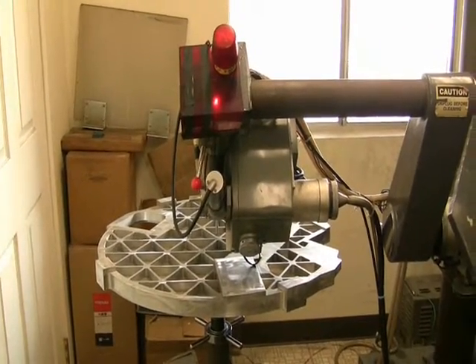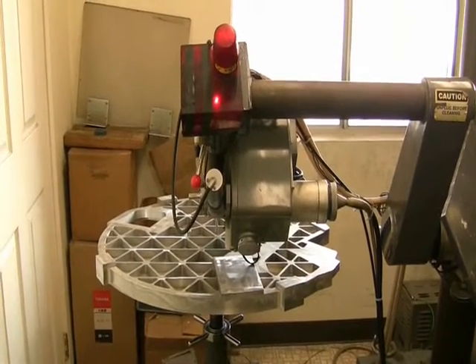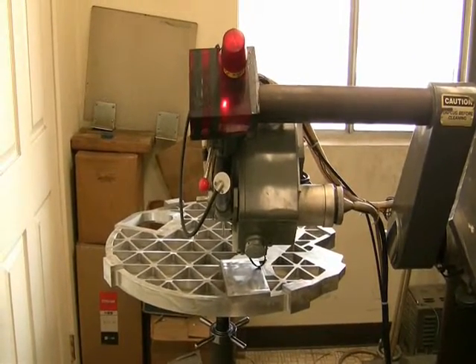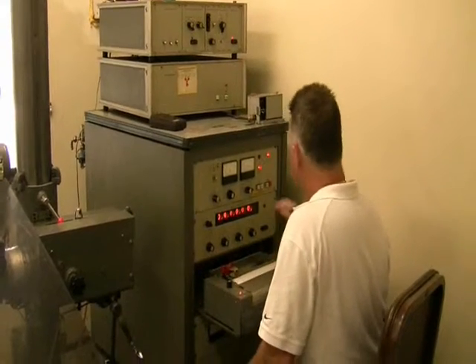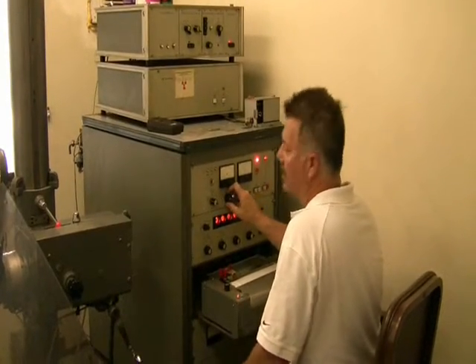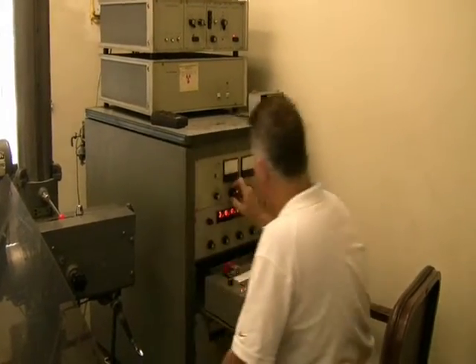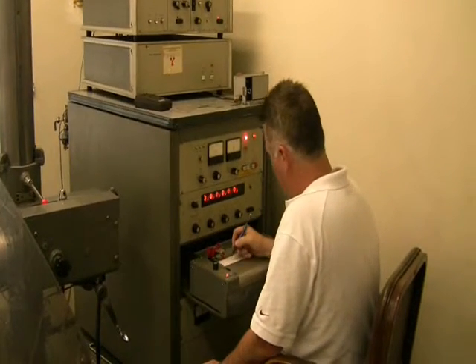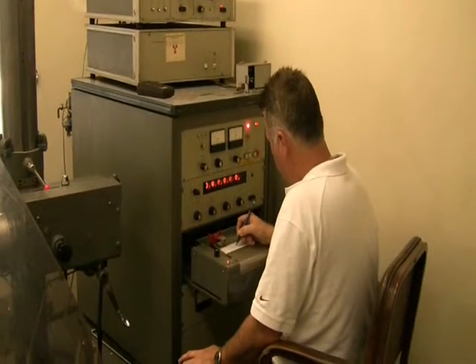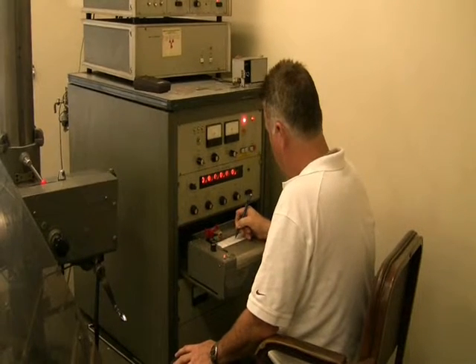starting the stress analysis. Measurements are taken at two angles, 45 and 90 degrees. The shift in the atomic spacing between the two angles is a direct function of the residual stress level left in the part.